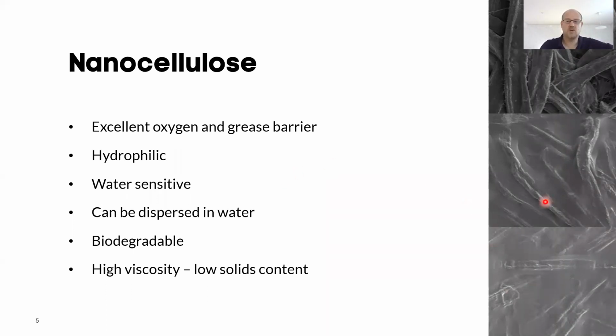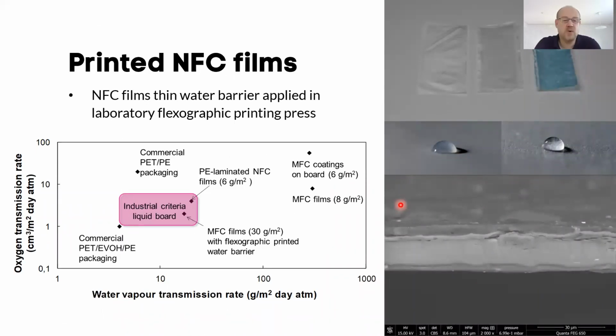On the other hand, you have quite good film formation properties, where you have quite nice films forming from it. One way to get around the water sensitivity, the simplest way, is just to put another barrier on, as we did. Here is what we would call a Friday afternoon experiment that we did a couple of years ago, where we took a water barrier and printed onto an NFC film. You can see the ones on the top. This is the unprinted, the printed, and we also put some pigment into the barrier just to see the coverage. It's a very thin film here. We printed twice on each side.